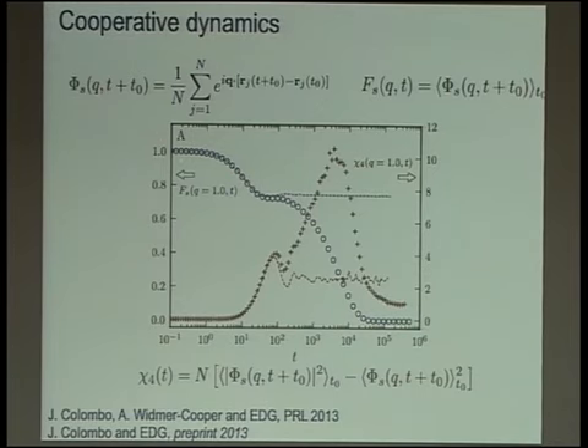Okay, so it has this initial decay, which again is dictated by the specific microscopic dynamics that we use, and then finally it reaches a constant value because the network does not restructure over time. Okay, so I just want to stress that this network is actually an elastic solid. So if we deform it, we can measure a finite elastic modulus at low shear rates, that is not significantly dependent on the shear rate.